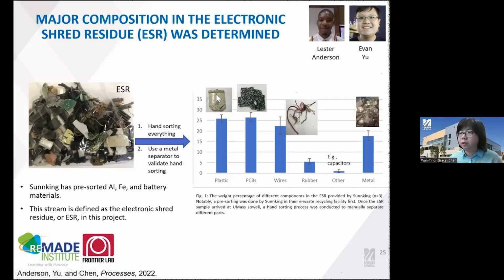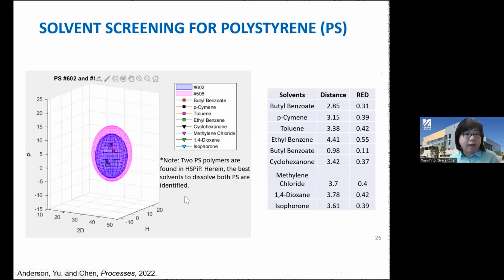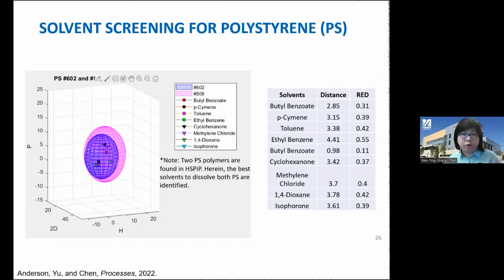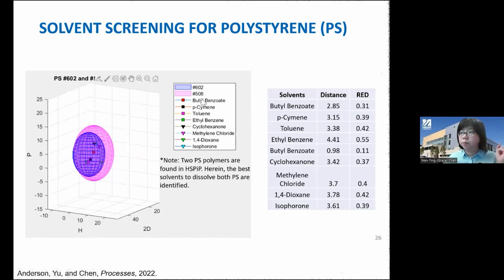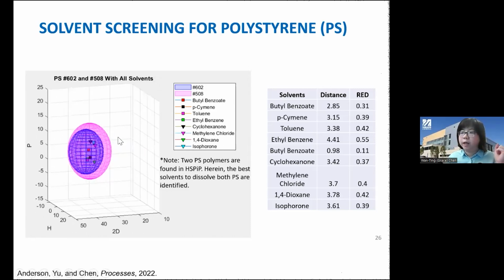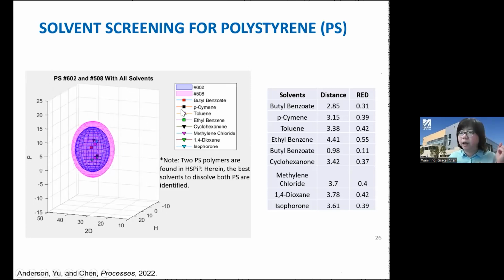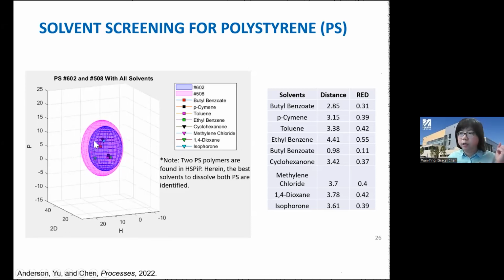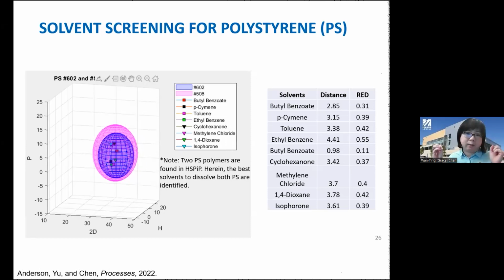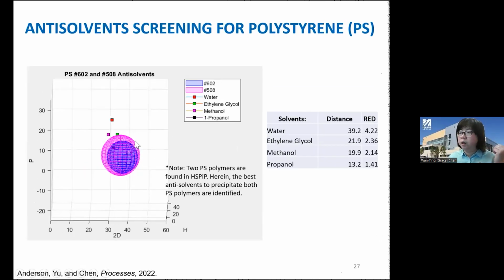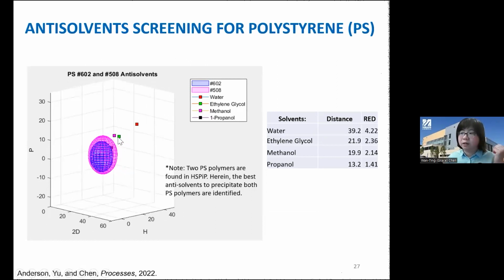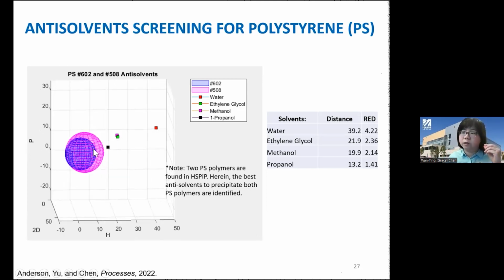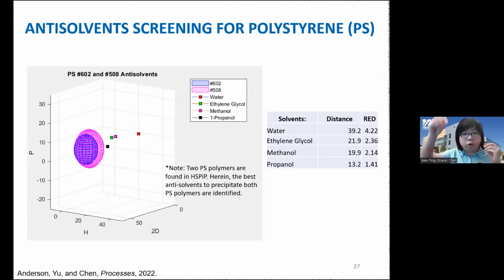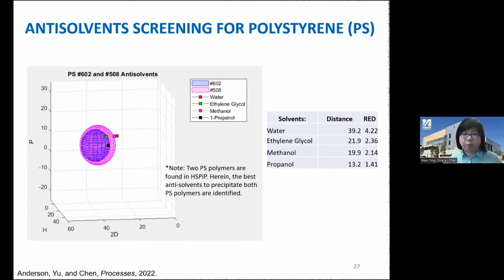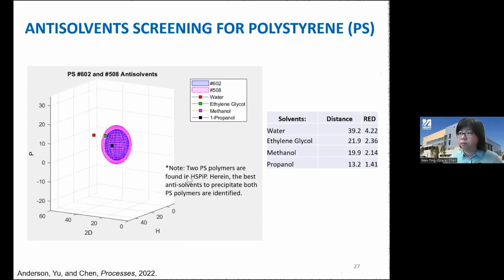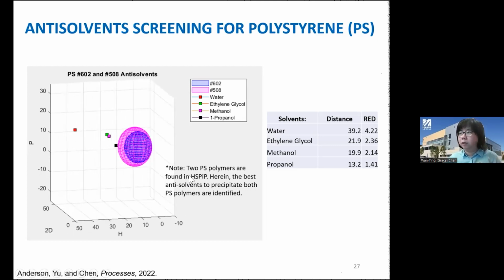With this polystyrene in mind, we take advantage of the Hansen solubility parameters that I just showed you, the Google Map in the polymer science world. And then in the database, we found that there are at least two kinds of polystyrene we can find. And based on that, we'll be able to identify some solvent that will work in terms of dissolving and extracting this specific polymer, PS, or polystyrene in this case. We can also identify the so-called anti-solvent or non-solvent, which is far, far away from the center of this polymer. This means that once we add a drop in a solution, we'll be able to bring this polymer back. And we call this technology dissolution precipitation. And I'm going to show you how we use this in a real-world application.